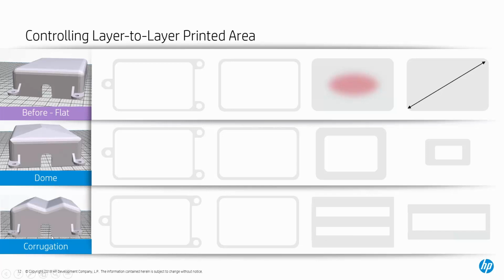And two different solutions that we see here: one would be a dome and the other would be a corrugation. But when we start to cut the part into 2D layers, and as we get to that larger mass part towards the top, you can see that we're eliminating that area where we would actually have a heat spot on top of the part. And as a result, you end up with a better part.